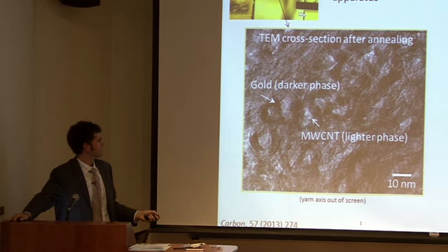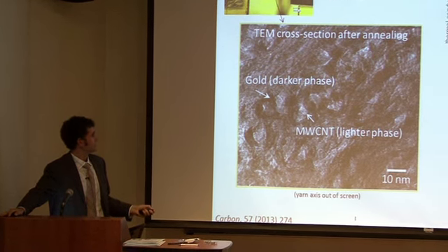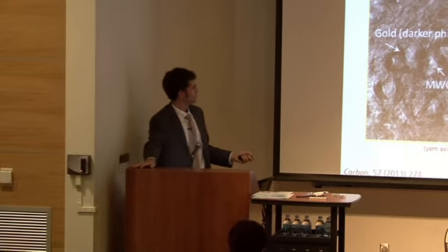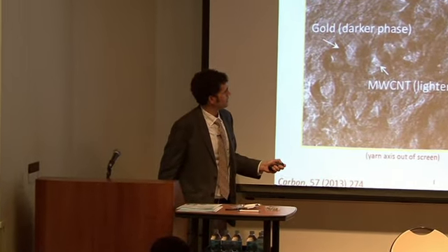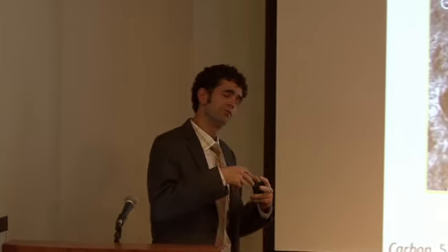We're in this regime of length and aspect ratio of the carbon nanotubes. The laser is kind of weak right now. But this is a regime where friction, inter-tube friction, really dictates the strength. And you can imagine how making the tubes bumpy by really increasing the surface area increases that inter-tube friction.